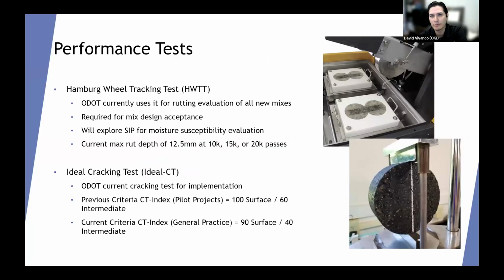The performance test we use in our BMD approach is Hamburg for rutting. We've been running Hamburg for about 20 years already, so we're very familiar with Hamburg. We consider not to have really a rutting issue in the state. So we will continue with Hamburg during design. We don't run it during production, but again we don't really see a rutting issue, so I don't think we should do much Hamburg testing in the field. And in terms of cracking, we do Ideal-CT. It's the one we're using so far.